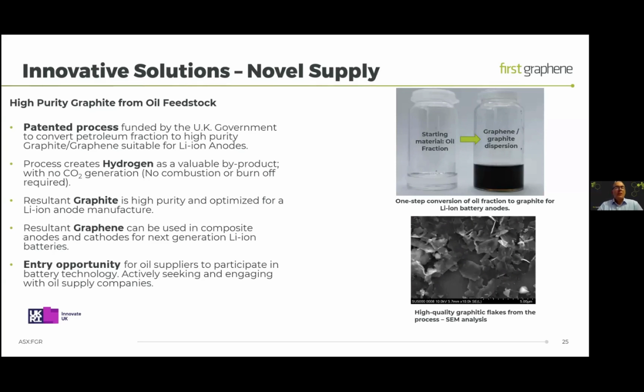There is obviously chemistry going on here, and the byproduct from the chemistry is hydrogen, which is really interesting. So it's a hydrogen byproduct. There is no associated generation of carbon dioxide with this hydrogen. So it's a sustainable route to hydrogen, ironically from a hydrocarbon feedstock. The resultant graphite, and the bottom image here shows you the high level of crystallinity that's possible in these graphite materials.